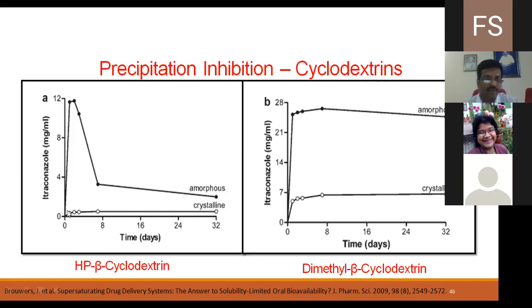See, in the beginning, we can see the spring effect. Solubility is increased, but afterwards, supersaturation is maintained, but it is not sustained for a long time. Though it is sustained, it is to less extent. Here, this represents the crystalline drug without any cyclodextrin, and this represents with the cyclodextrin. So when compared to the crystalline compound solubility, we can see the spring effect, increased effect.